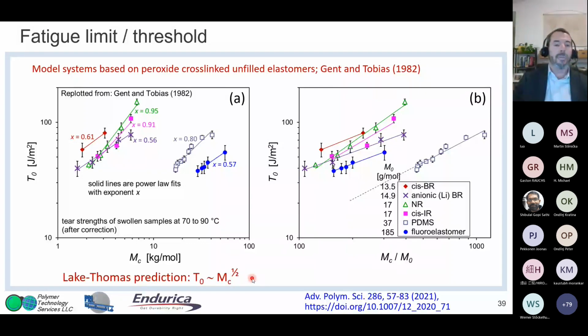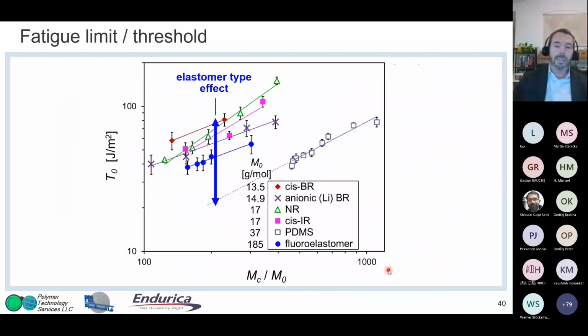And then the elastomer type effect, it's a lot easier when you normalize the M sub C by the M sub 0 for the polymer, and that's what's done over here. So this is converted to here simply by dividing by M sub 0, and I'm going to show that on the next slide, so we can look at elastomer type effects. And what you see is, out of all of these elastomers, the best is butadiene rubber, cis butadiene rubber. Below that is natural rubber, and really at the very bottom are things like silicone materials and fluoroelastomers.